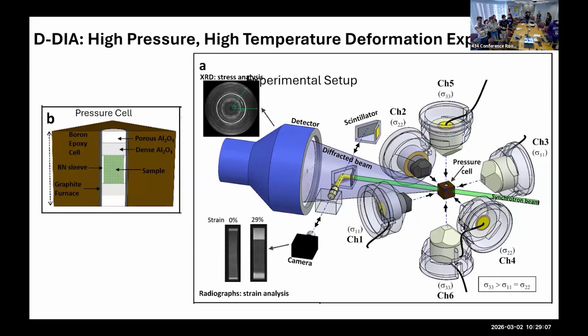This black cylinder will be inserted into this hole in the cell. So you have this black cylinder here, it goes in the hole and it goes down here. And then we run a current through the anvil, through this furnace. When we run a current through this graphite furnace here, it'll heat up. So that's how we heat up our cells. And then on either side, we have these pieces of Al2O3. You see these little pucks.